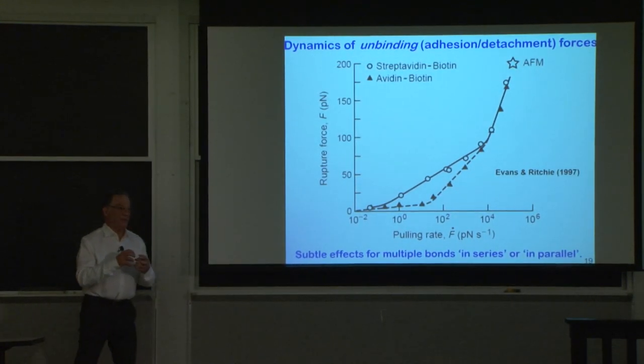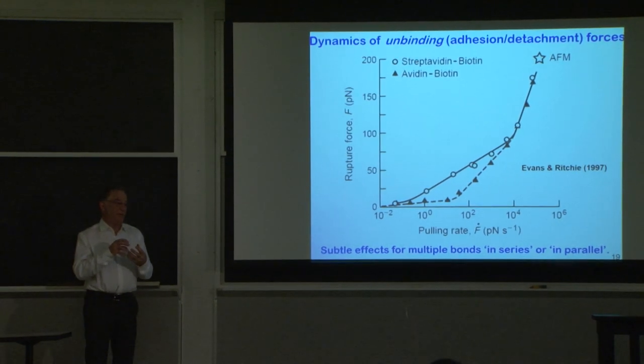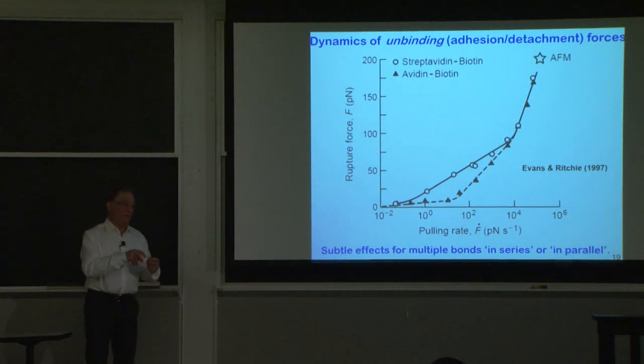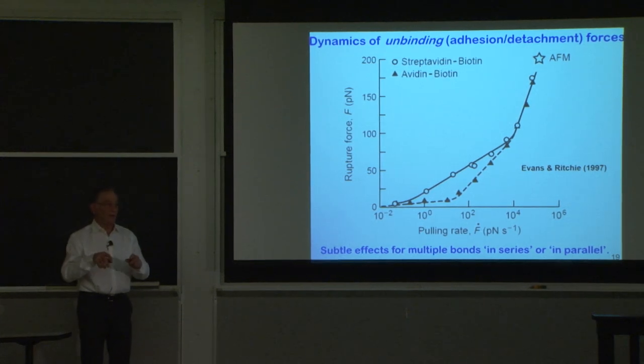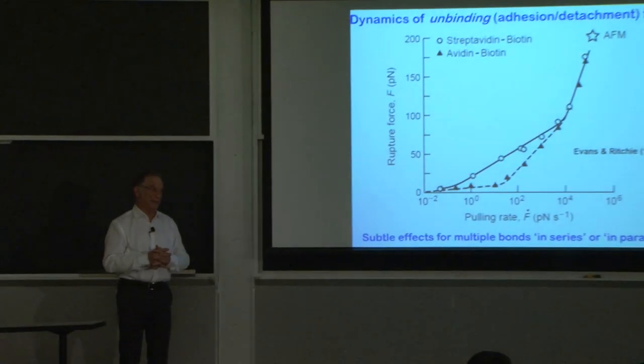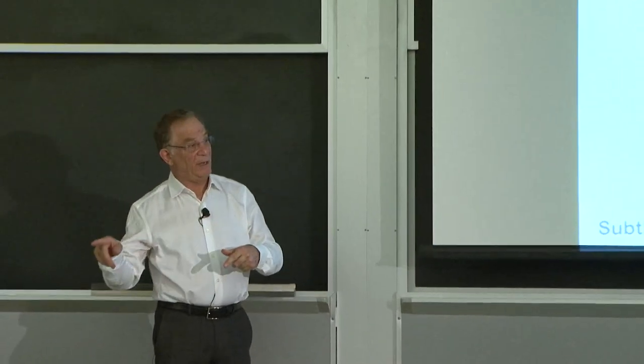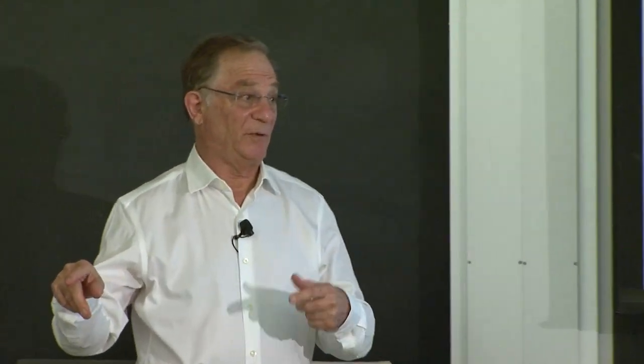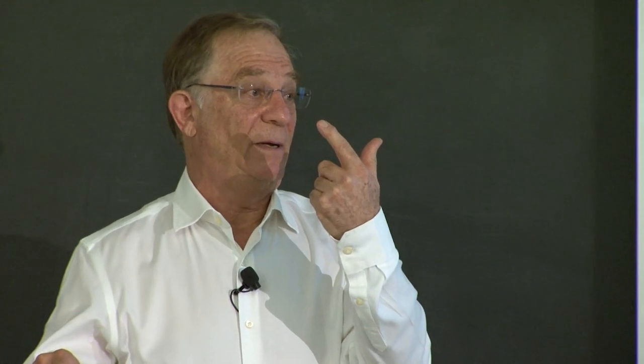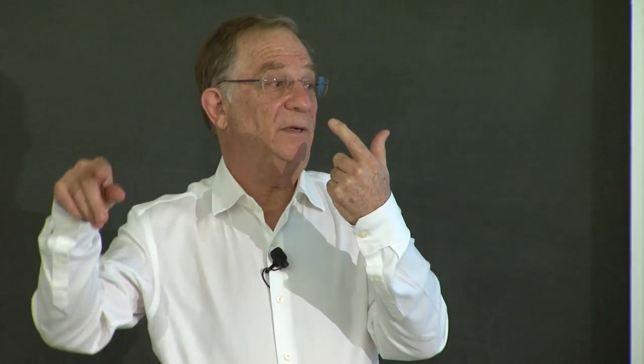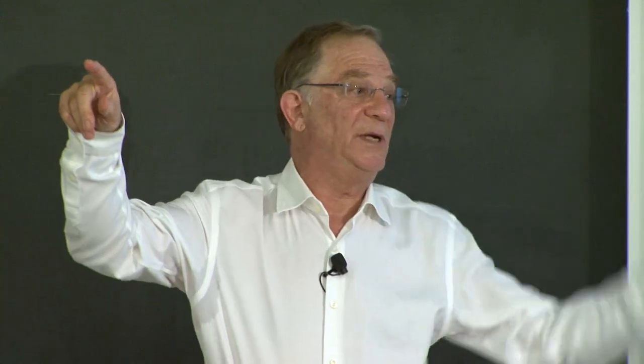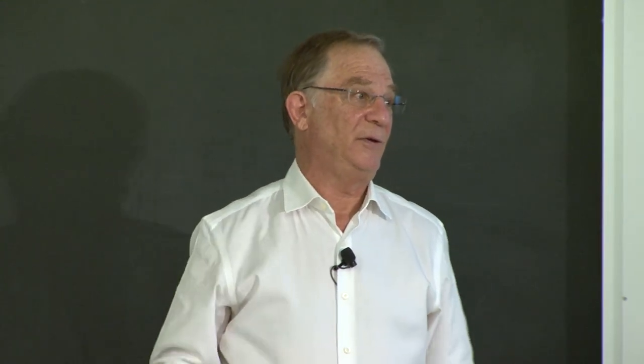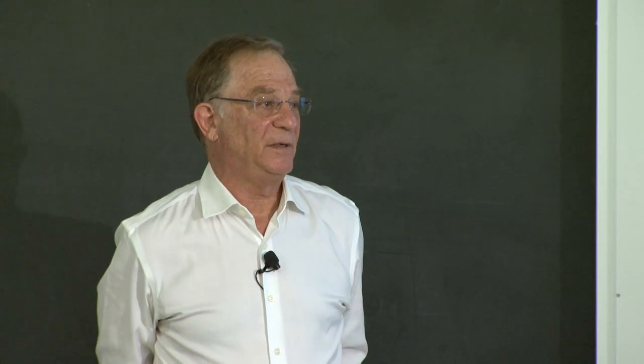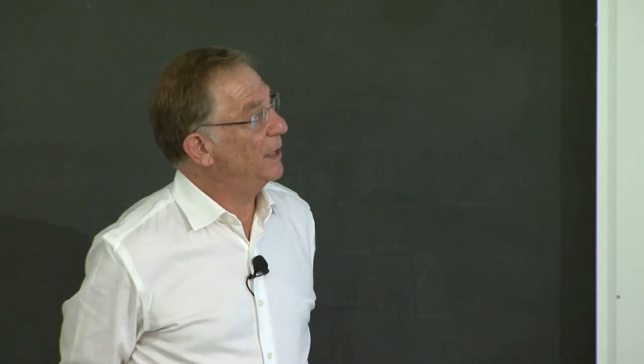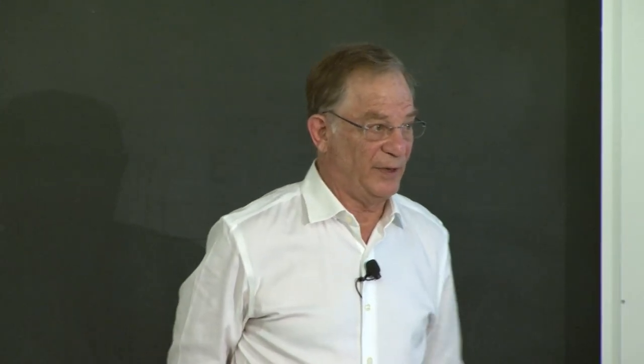A tether may have two or three binding sites, and they either penetrate the surface or lie down on the surface, and you've got to pull the whole thing off. It gets very complicated. And when you've got other bonds nearby, it gets even more complicated, because this one has come off, and before you know it, this one comes off, but this one, meanwhile, has come back again. So it's very difficult to interpret the results, except the general trend is always the same.